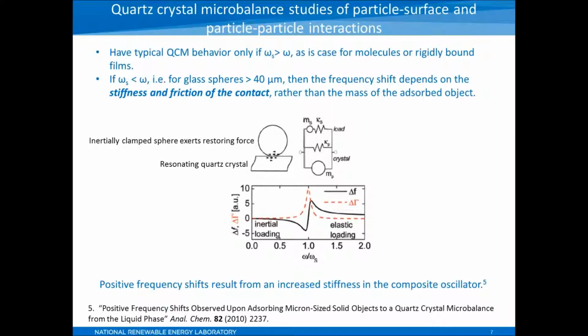If you have large particles, in this case glass spheres that are larger than about 40 microns, then what happens is inertia clamps the particles in place while the resonator moves underneath them, and the particles essentially exert a restoring force on the crystal, which effectively increases the stiffness of the resonator.